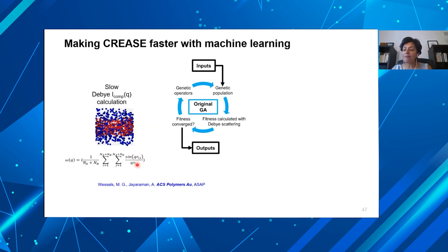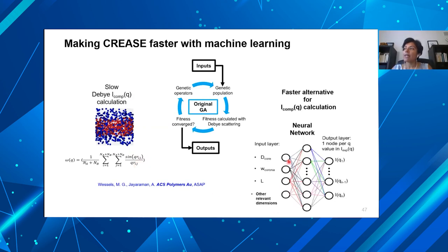So if we could have a machine learning model that takes the dimensions of that structure, say in this case, it's the diameter of the core, the thickness of the corona, the length of the cylinder, it could be different for the vesicles. And then that machine learning model directly converts it to an I_comp(q). You're not doing any of these calculations. It's super fast then. So we did do that.